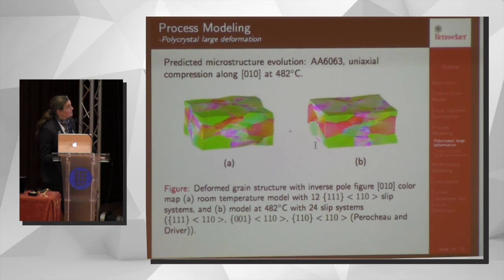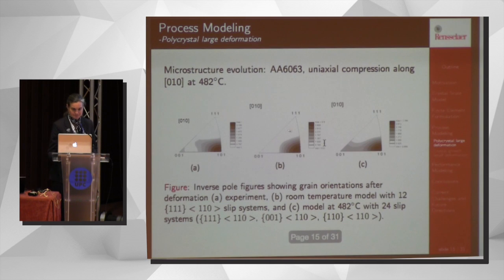When we have these 24 slip systems active, we see, again, evolution of the texture, but less misorientations within the grains, and also we see a more homogeneous deformation. And what we were really interested in is that in subsequent recrystallization, the 001 orientation is the dominant one that appears. And when you only consider 12 slip systems, you just don't see 001 orientations appearing after the deformation, and that's what we see here. But in the experiments, it's clear that there is a 001 component, and that's a favorable orientation for nucleation of new grains and growth. And we do get that orientation appearing when we include all 24 slip systems. So we see something that's more close to the experimental observation when we include those additional slip systems.